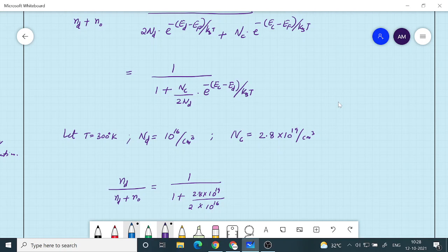You see that this is around 1000 into the exponential. It's a negative one. Ec is going to be greater than Ed, and to be more exact, I should give that also. Ec minus Ed for a particular atom, that is phosphorus in silicon, is going to be equal to 0.045 electron volt. I told you it is from 0.01 to 0.05 electron volt. So if it is phosphorus in silicon, it is 0.045 by kBT. kBT will be 0.0259. So this is what we need to evaluate.